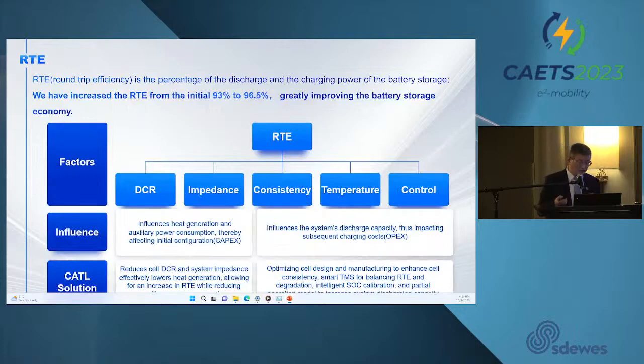RTE, round-trip efficiency. This is a ratio of the discharged energy to the charged energy. We call this RTE. By reducing the cell resistance, or DCR, and the system impedance, and by implementing new technologies such as intelligent state-of-charge calibration, we have increased the RTE from the initial 93% to currently 96.5%, greatly improving the competitiveness of lithium-ion battery for stationary storage.